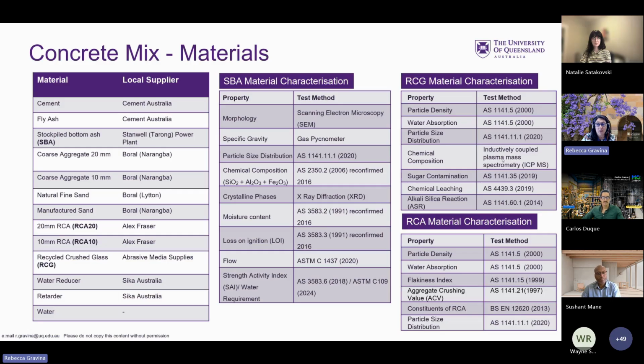In terms of the recycled crushed aggregates, particle density, water absorption, the flakiness tests, and the aggregate crushing value are all very important, as well as the different constituents that make up the recycled concrete aggregate. It's very important that the type of recycled aggregate that you use is strong enough and can fit the properties and requirements that are needed, as well as the particle size distribution. We'll talk a little bit more about that also.